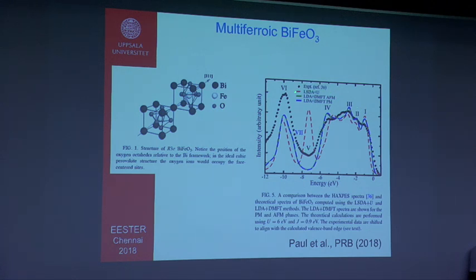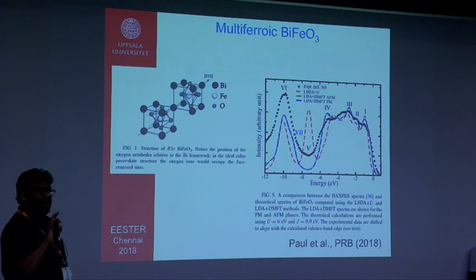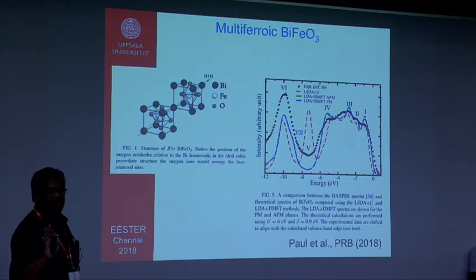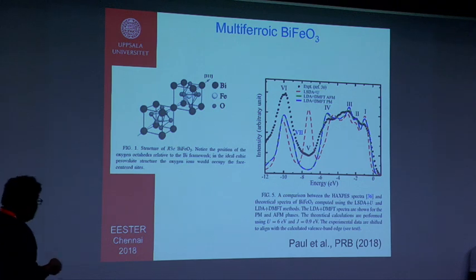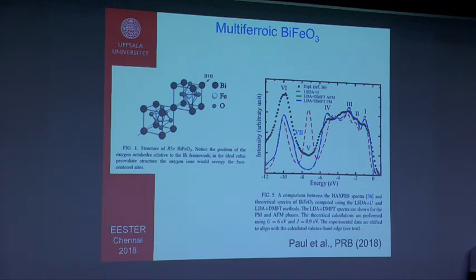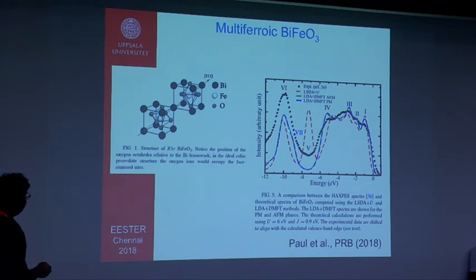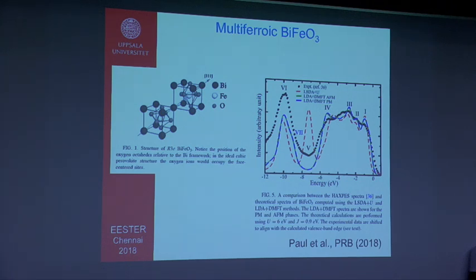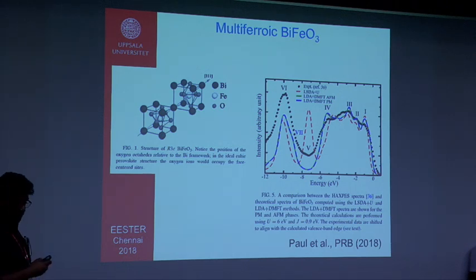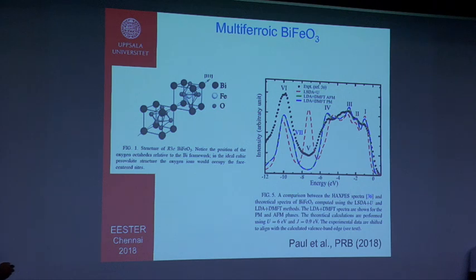So you see the LSDA plus U result is the red curve here. There is a peak here which does not exist in the experiment. Previously people thought that LSDA plus U is absolutely good for bismuth ferrite. Quite a lot of papers are there. But when we did that, it was a surprise to us that this is really not so good. If you do DMFT, then you see that the peaks more or less match very well with the experiments. So this is one example where dynamical mean field theory is winning over the static version, which is LDA plus U. If you're interested, you can have a look into the paper.